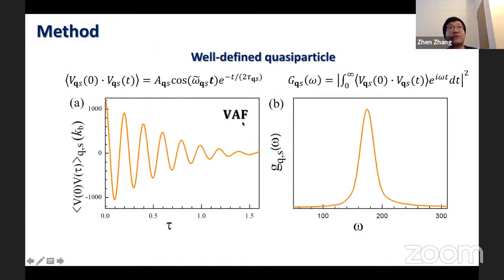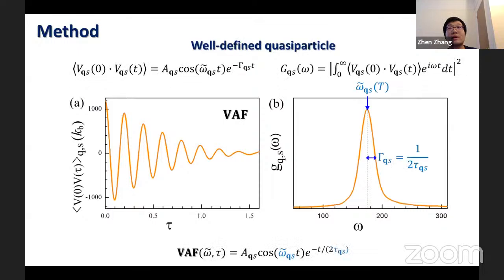For a well-defined phonon quasi-particle, the velocity autocorrelation function is an exponentially decaying cosine function, which looks like this. The single phonon power spectrum can be obtained by Fourier transform of the VAF. For a well-defined phonon quasi-particle, its power spectrum has a Lorentzian line shape with a single peak at the renormalized frequency omega tilde, and the lifetime of tau, and the line width of 1/2 tau.